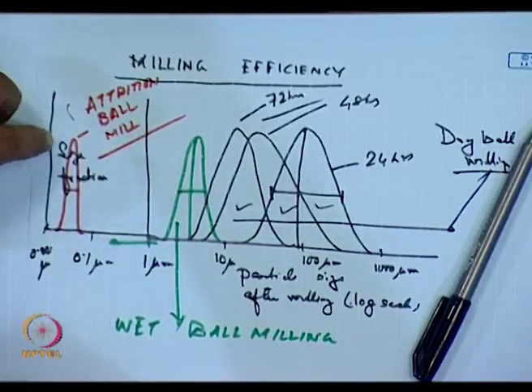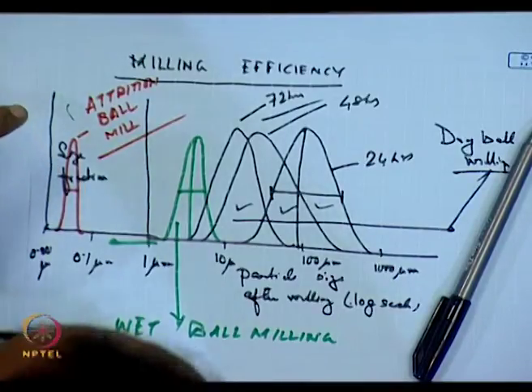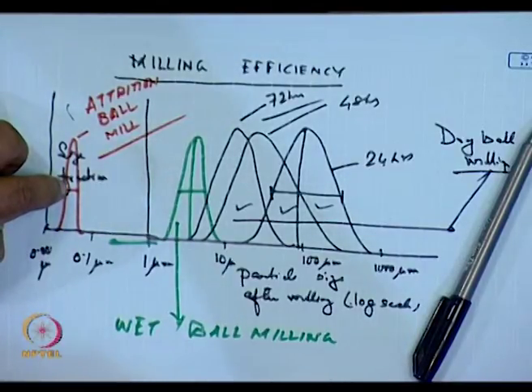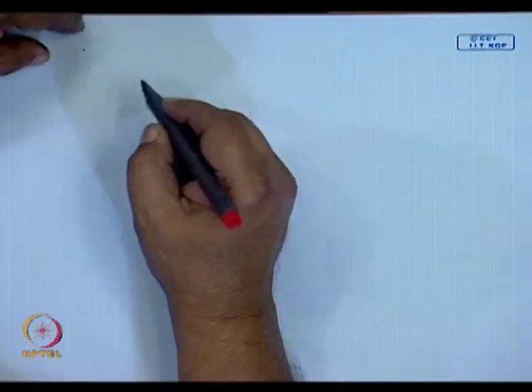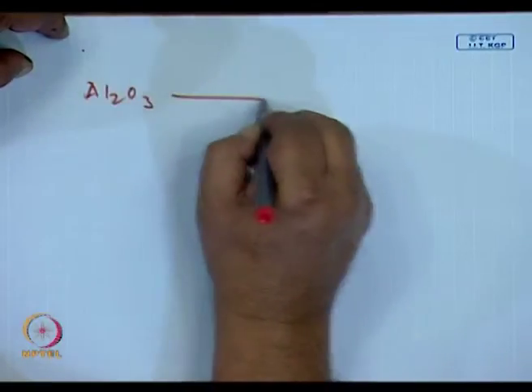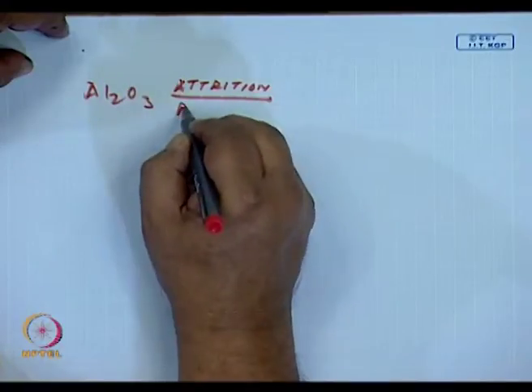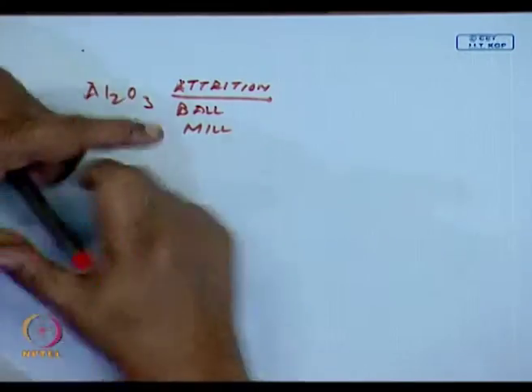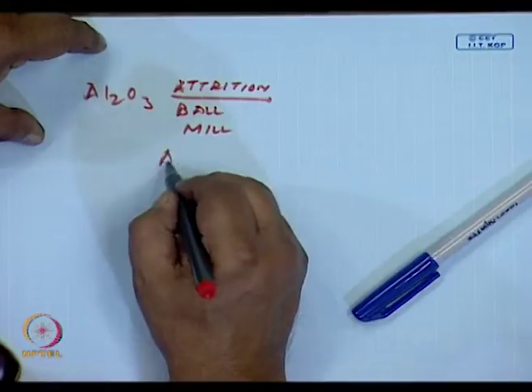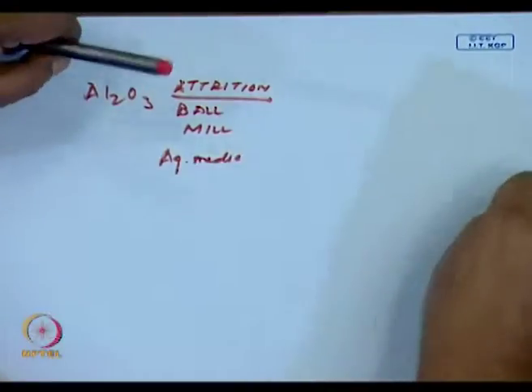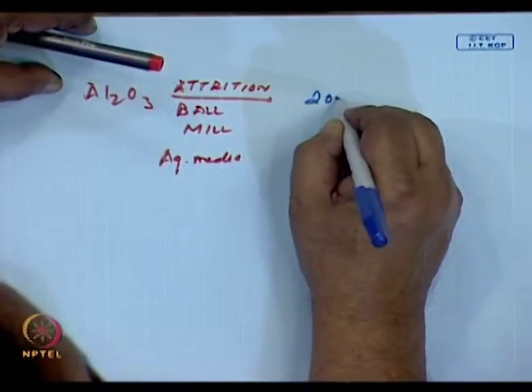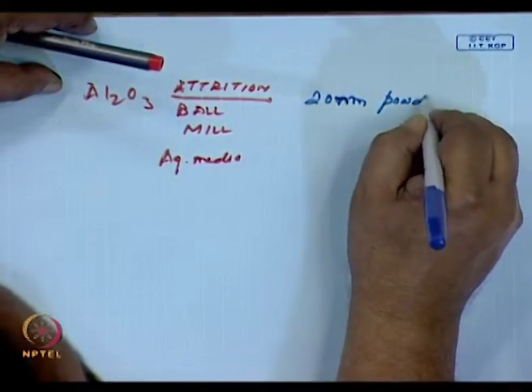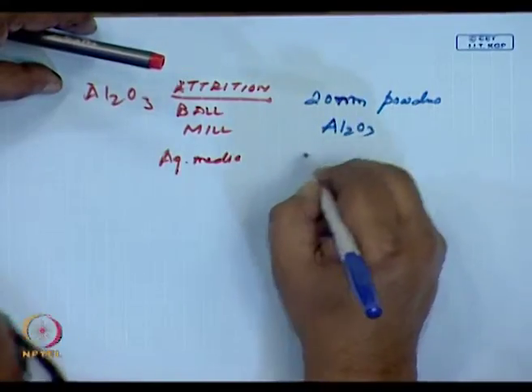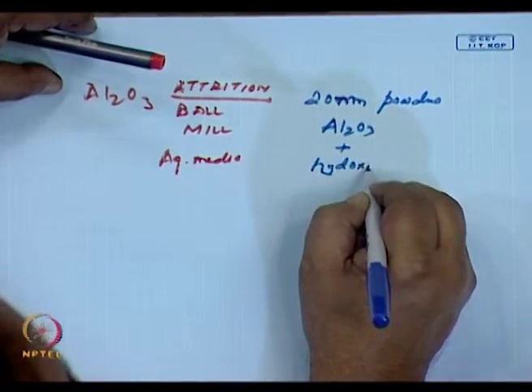And the advantage of having narrow particle size distribution means we can take the powder as is received. Yes, there are many issues over here. Like say if I was attrition ball milling alumina in aqueous media, I could get 20 nanometer powders, but then it would be a mixture of Al2O3 plus hydroxides of alumina.